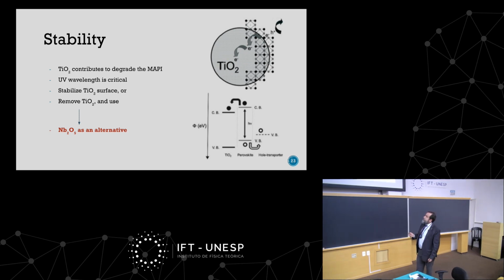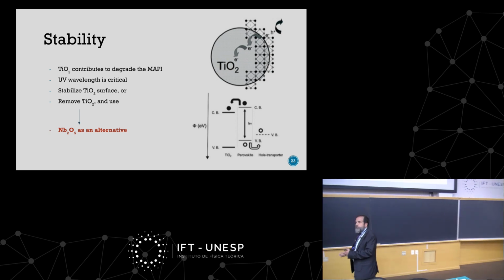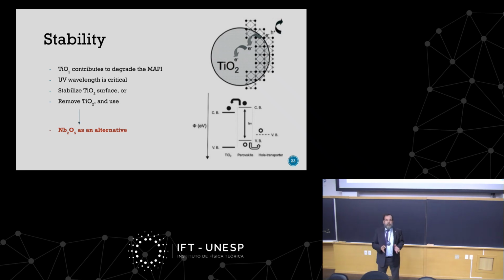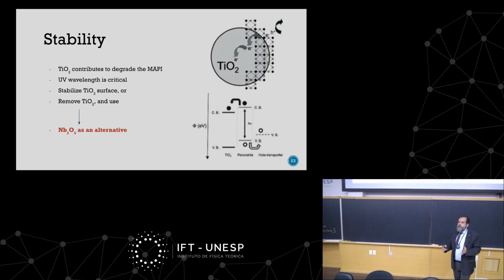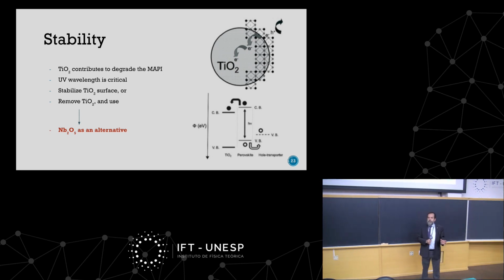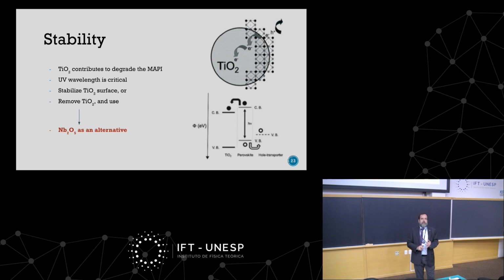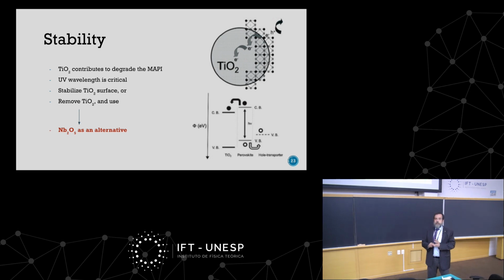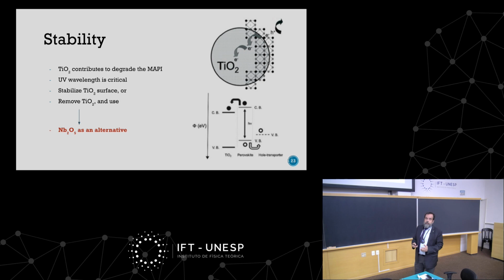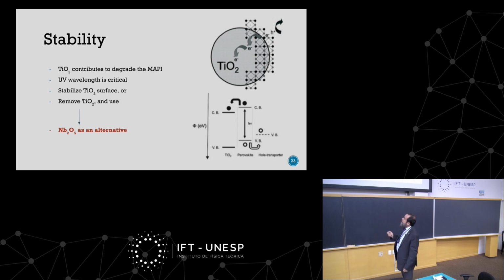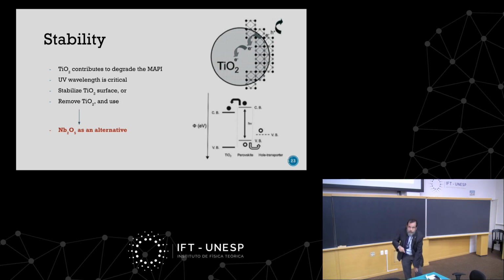And it actually has a problem with TiO2, because I didn't go into too much detail, but these solar cells are not as stable as silicon, so they have degradation. And the challenge of these 20 papers per day that I told you on perovskite is basically trying to solve this, to make them stable. And there is another effect which is called hysteresis, which I'm going to talk about, that we're trying to get rid of. And TiO2 may be a component that is responsible for the degradation of this material, because it's well known from the chemistry that TiO2 is very effective in photoreactions.